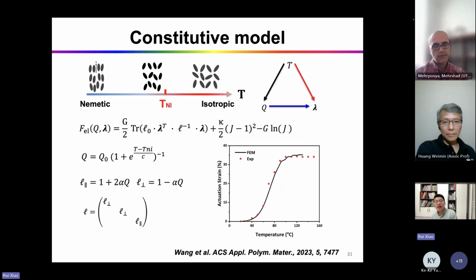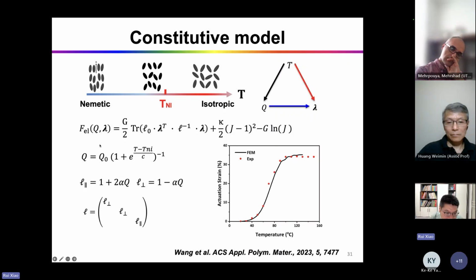For modeling, we just need to introduce the orientation of the mesogens into the classic mechanics model, and we also need to model the nematic-isotropic transition. So we use phenomenological equations to model these transitions.